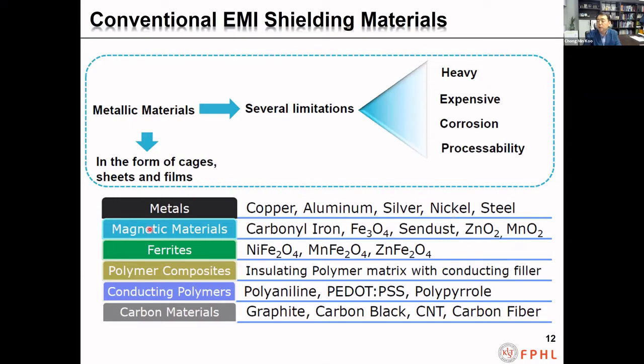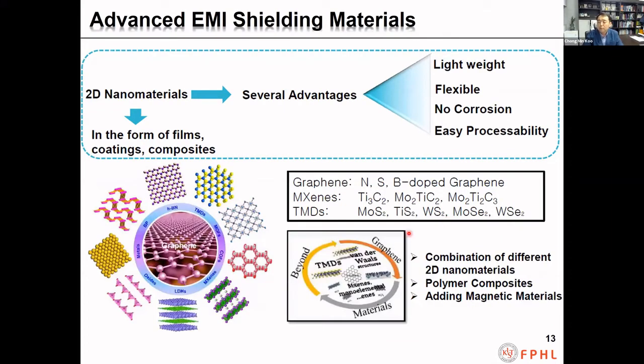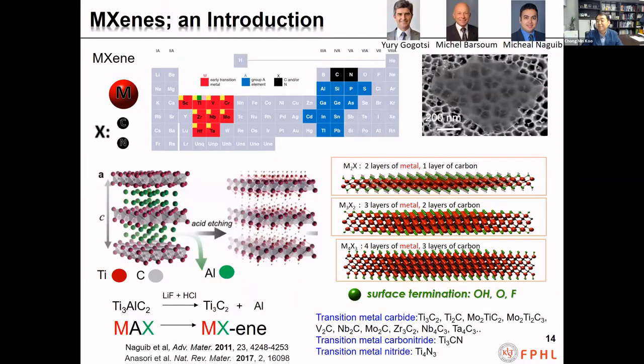Among shielding materials, pure metal film is the most popular EMI shielding material because it has high electrical conductivity. However, metal film is not very suitable for highly integrated, smart, flexible electronics because of its heavy weight, high cost, and poor processability, especially the poor coating processability on uneven substrate shapes. 2D materials have been considered as promising candidates for lightweight shielding applications. Among them, MXene is the most promising candidate.